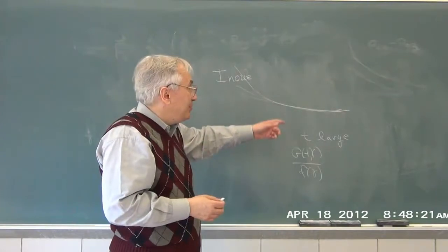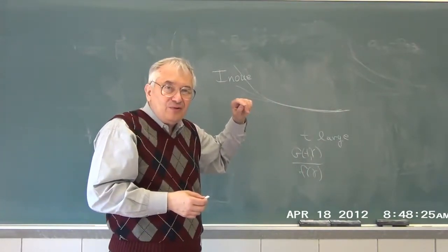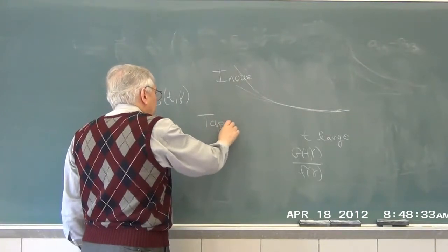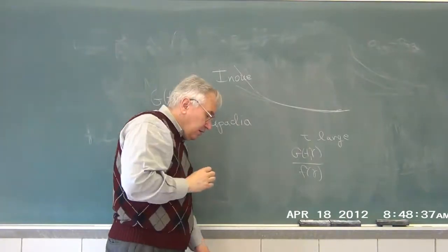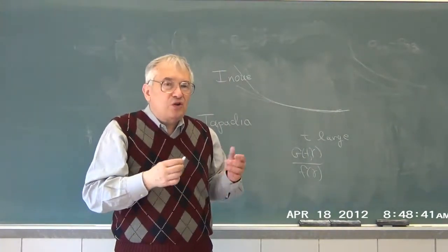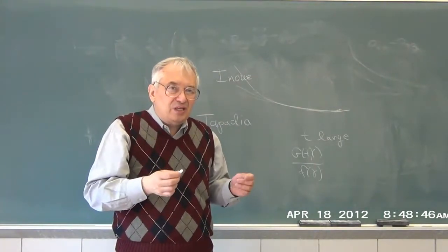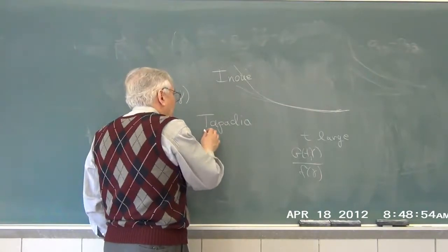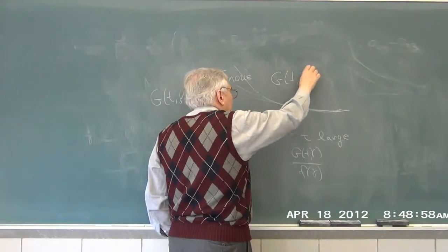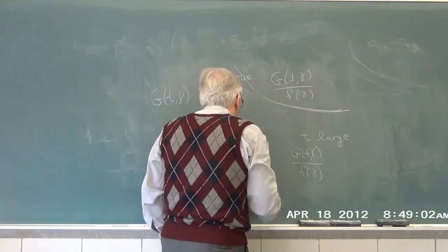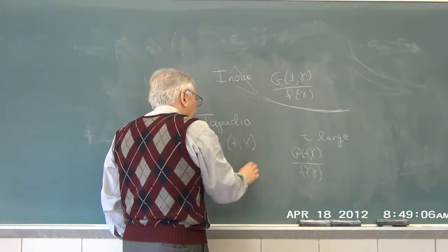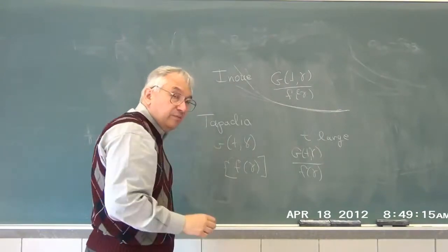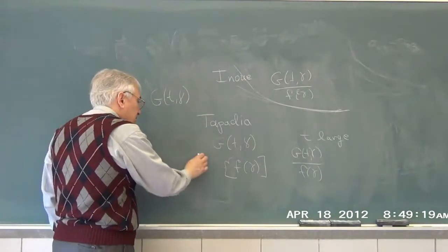And I don't believe there's any disagreement that if you do the mathematics, the curve moving around this way, you do see this. However, there is also the nice set of experiments by Tapadia. And the analysis by Tapadia shows what happens if you start with the measurements themselves and look at the measurements themselves and don't overprocess them before you look at them. Because what they did is they plot not g of t and gamma over this function of gamma, but what they did was to look at g of t and gamma. And implicitly that's the same as saying they're going to look at and ask what f of gamma is. And what they demonstrate is f of gamma is not